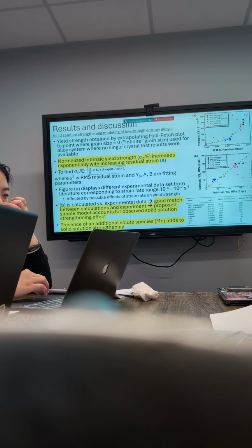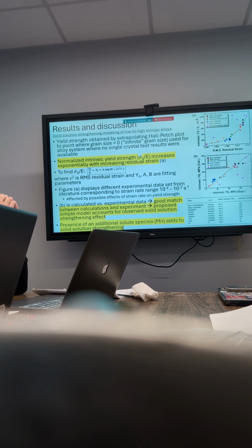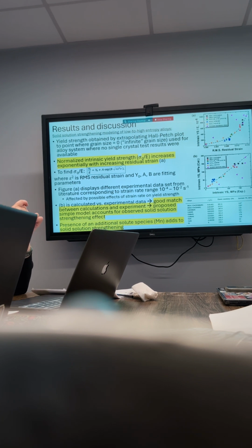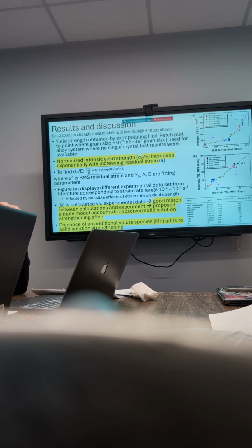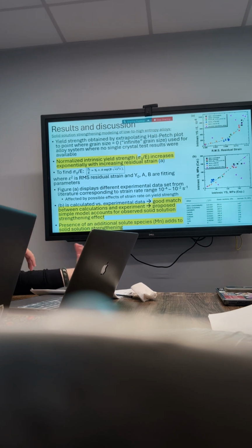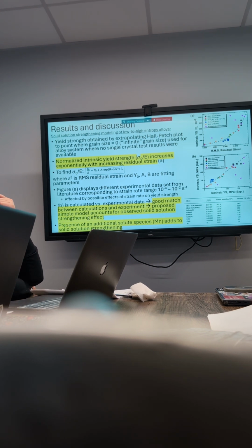They mentioned that they wanted to do a constant strain rate, but they're showing a slight range, which I think they were trying to keep constant and couldn't, so this ended up being the range that they did their experiments at. I think it's fine. I don't think this is a significant change in range that would really affect the conclusions that came from this data. And then the middle plot is calculated versus experimental data, and since it's pretty clearly one linear match, they had a good match between calculations and experiment. So it's good for them.